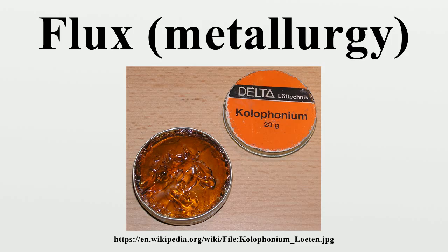As cleaning agents, fluxes facilitate soldering, brazing, and welding by removing oxidation from the metals to be joined. Common fluxes are ammonium chloride or rosin for soldering tin, hydrochloric acid and zinc chloride for soldering galvanized iron, and borax for brazing, braze welding ferrous metals, and forge welding.